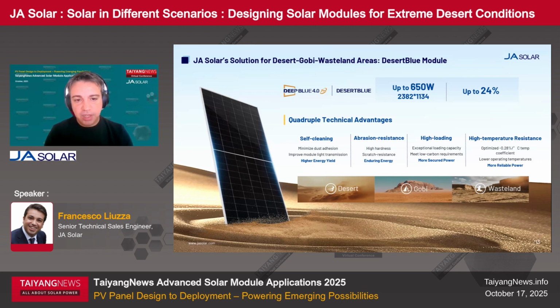Four technical advantages were improved, especially the self-cleaning property of the modules, minimizing dust adhesion, and improved module light transmission. The product also offers higher abrasion resistance on the coating, high loading capability and capacity, lower carbon footprint requirements and targets, and also improved high temperature resistance. Right now, the coefficient is down to 0.28% per Celsius degree, later down to 0.26 in the 5.0 generation.